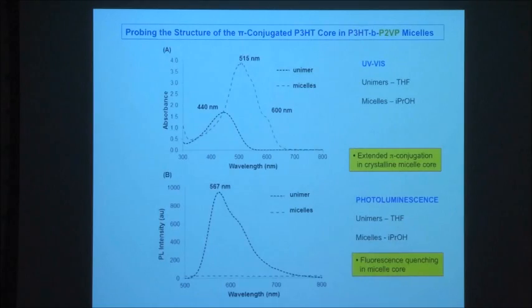If you look at the cylinders you generate, you can show that you have extended pi conjugation in the core of the micelle. So if we're going to look at charge transport, electronic properties, think of these as nanowires, for example. You need to have a high order in the core. If you look at the UV-vis, as you go from unimers to micelles, you get this red shift. And there's this telltale shoulder here, which is indicative of a crystalline core for the poly-3-hexylthiophene. This is well known in the literature. And you get this shift as you get extended pi conjugation. And as you go from unimer to micelles, you get fluorescence quenching, and this is also what you'd expect for these structures.